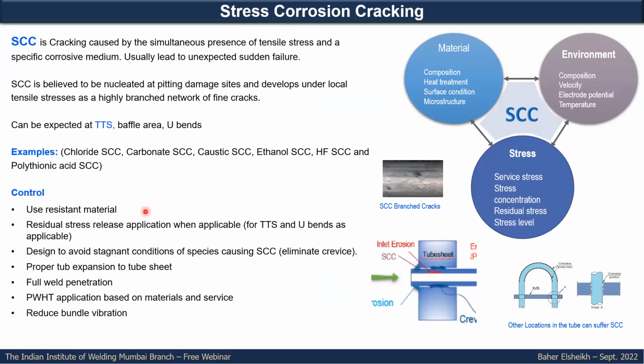To avoid and control that, you might need to use a more resistant material. You need to avoid residual stresses, so think about the way you apply the weld, the expansion ratio, and having a clearance between the expanded part of the tube and the weld. Don't apply the expansion up to the weld or with minor clearance to the weld, or you'll have higher residual stresses or stress concentration in this area. And apply the proper expansion.